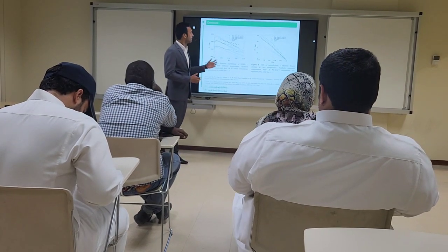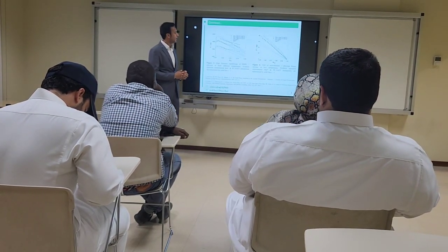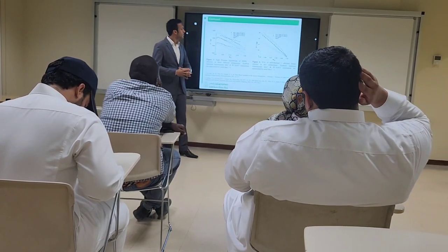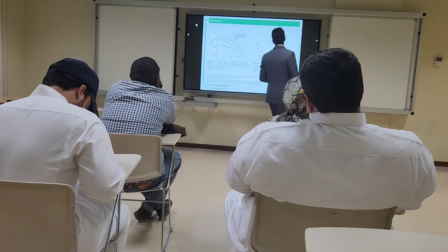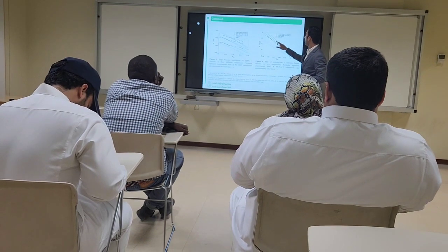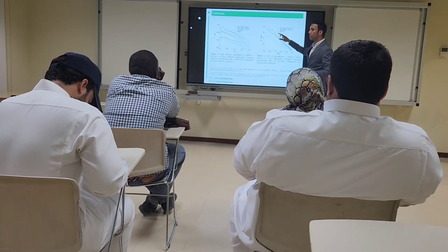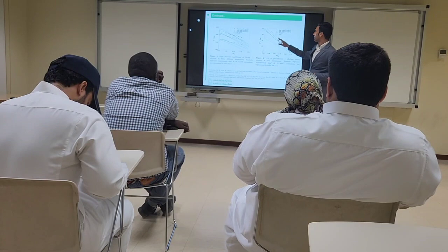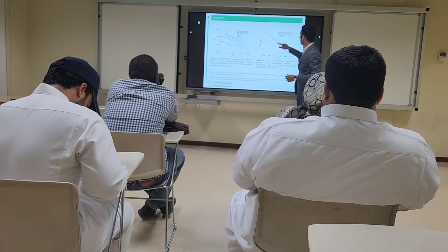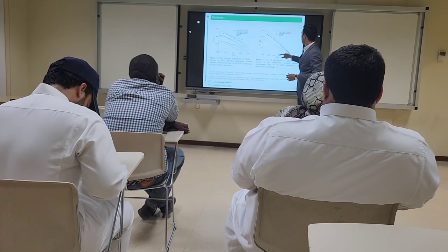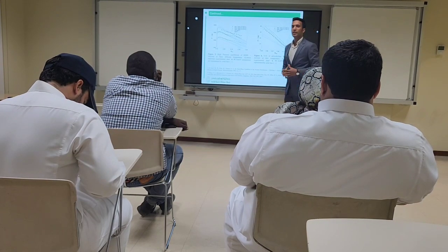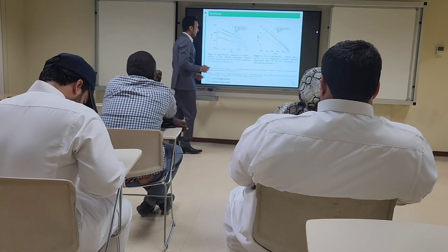Similarly, this is the vapor liquid equilibrium of polyethylene with ethylene binary mixture, and the references are given. We can see that, let's say we are at a high temperature of 155 degrees, what will be the solubility of polyethylene in ethylene solvent? If the pressure is 40 bar, the polyethylene fraction is higher for the case of the high temperature, which means the solubility is lower for the ethylene solvent.